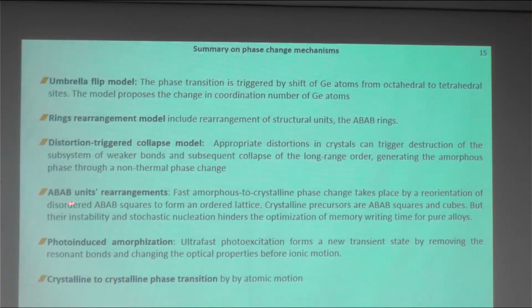Again, ABAB units rearrangement. Here more theoretical work was done, and it was shown that if you want to crystallize your system, first you need to form such ABAB squares, and this acts as a nucleus, and then they form squares and cubes, and then they transform to the stable nucleus, and then the system starts to crystallize. But the problem here is the nucleation. This is a non-homogeneous, stochastic process, and this hinders the optimization of memory time for pure alloy. So we need some ideas how to stabilize this nucleus.